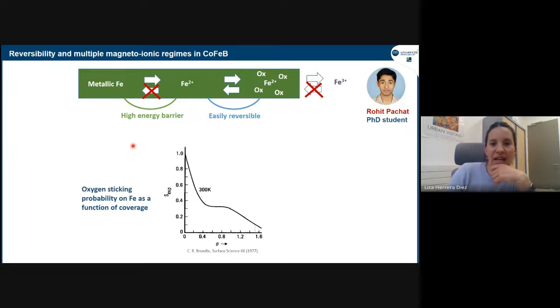And this is something that we can relate to, for example, the sticking probability of oxygen on iron that has been shown a very long time ago. So it has this profile. When there is no oxygen in the system, there is a fast decay of the sticking probability as oxygen is added to the layer, which could be related to an Fe2+ type of electrochemical reaction, if we want to call it that way. After that, there is kind of a flat line where we add more oxygen, but it doesn't really affect the sticking probability of that oxygen.